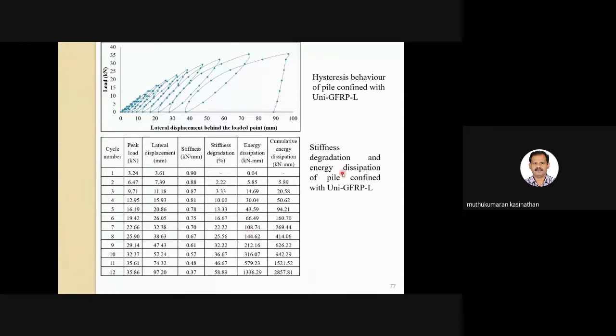You can see here, this is the unidirectional fiber. The direction is unidirectional, and glass fiber in the longitudinal arrangement. As we know, the longitudinal arrangement is better than the circumferential arrangement. And this is pertaining to the glass fiber. You can see here, we are talking about the stiffness degradation. The stiffness degradation is almost 50% close to the 12th cycle, whereas the unconfined pile is close to 50% much earlier.